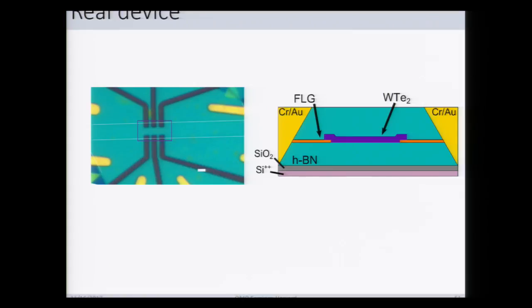So a real device will look something like this. This is a top-down optical microscopy image. This is in teal on the outside. This is where all the boron nitride was that encapsulates on top and bottom. We have etched here, you can see in the dark regions, so that in the center we have a Hall bar-like structure. And in purple is designating roughly the borders of the original tungsten telluride flake. So you can see that everywhere in the Hall bar we will have tungsten telluride for our 4-probe measurements.